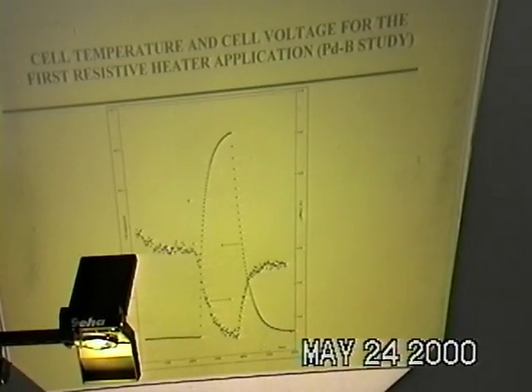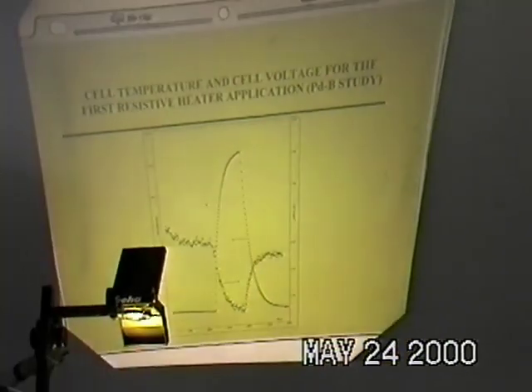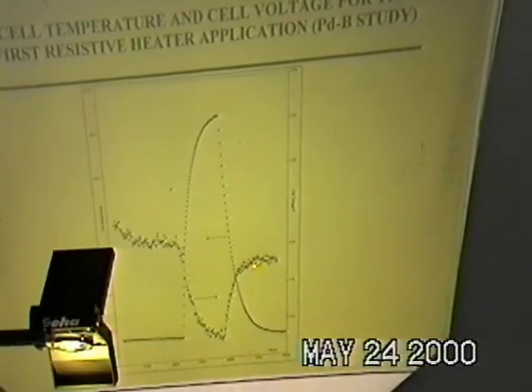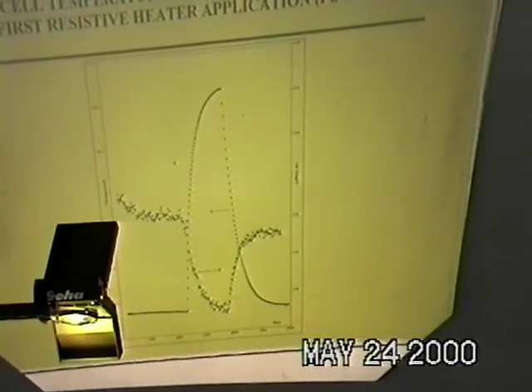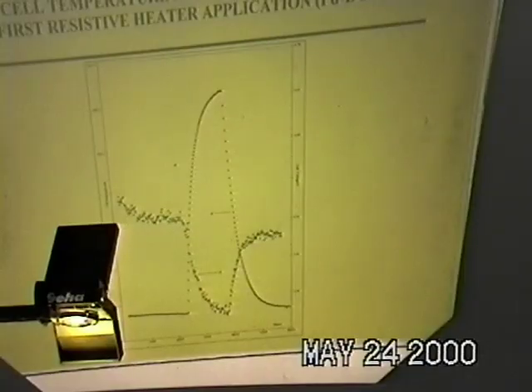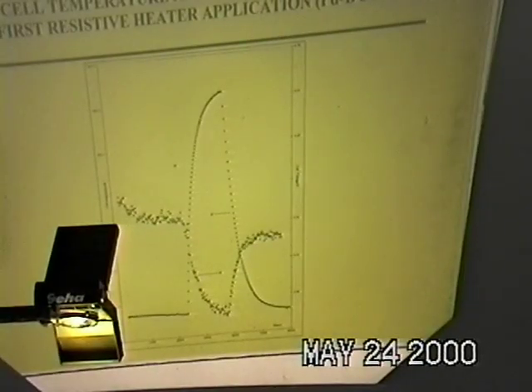This is the cell voltage. Of course, when the temperature goes up, the cell voltage goes down, as you would expect. And then when the temperature starts to fall, the cell voltage goes up again. But you should look at heating cycles like this and look for evidence of positive feedback, before you determine that you can use it for the calibration.